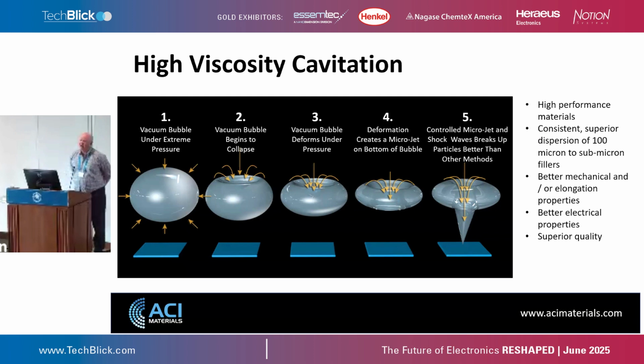If any of you know much about these particles, they often come agglomerated, and to really get the best performance out of them, you need to break up agglomerates and disperse them very, very evenly throughout the coating or the ink, the conductive ink or whatever, to get the best performance. And the way cavitation works, if you've ever seen a propeller on a speedboat, if you spin it too fast, you create vacuum bubbles, which then implode, and they start to erode the impeller. This is the same sort of theory behind high viscosity cavitation: we are forcing materials through and creating these small vacuum bubbles which create these very high energy jets that break agglomerates apart.